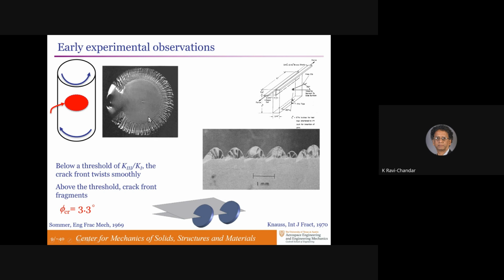Sommer did an even more interesting experiment. It was a very dominantly mode 1 experiment with an internal crack under pressure in a cylinder. So this is a cylindrical specimen. There's an internal crack with pressure in there. It grows radially out, but then he superposed a torque on it. That gives you the mode 3 along the crack front of uniform mode 3. And he found that when the mode 3 value reached a critical threshold, daughter cracks spawned out, and you had tilted cracks, or the echelons forming along the entire crack face.